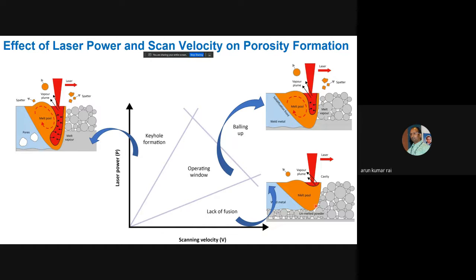You can see here, you will see the unmelted powder. Here down is not melted at all. Suppose my layer thickness or powder feed rate is high, okay, and scan velocity is less. So I am not giving enough time to melt. I am moving the laser very fast, so it is not getting time to melt the entire thing. So you will again have a porosity formation.